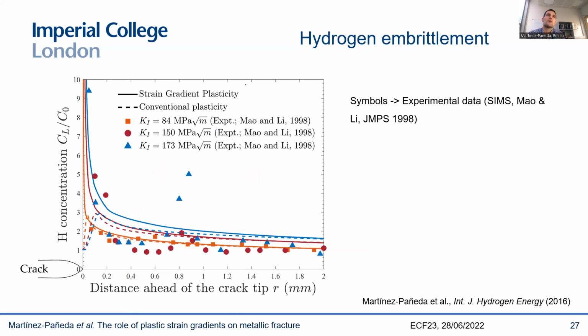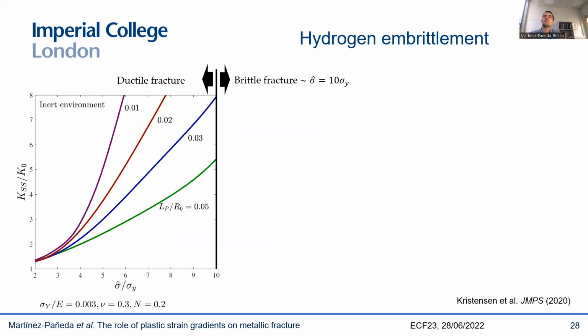And it's very difficult to measure hydrogen content so close to your crack tip, but there are some experimental data out there, and we can see that they seem to agree with what we predict with gradient plasticity. You can see here that the hydrogen concentration increases rather significantly as you approach the crack tip, where your conventional plasticity predictions are lying all the way here. And we use this rationale to try to understand the embrittlement process, because in embrittlement you basically have metals that fail in a ductile manner suddenly failing in a brittle fashion due to the exposure to hydrogen.